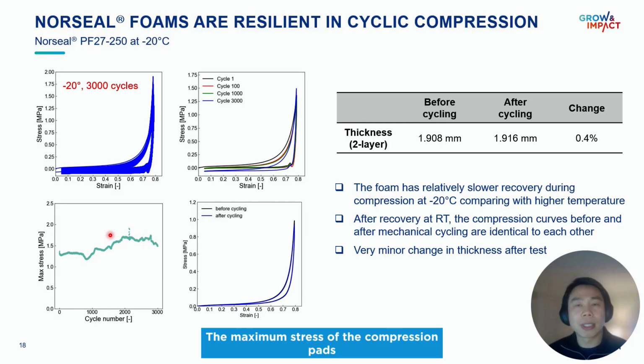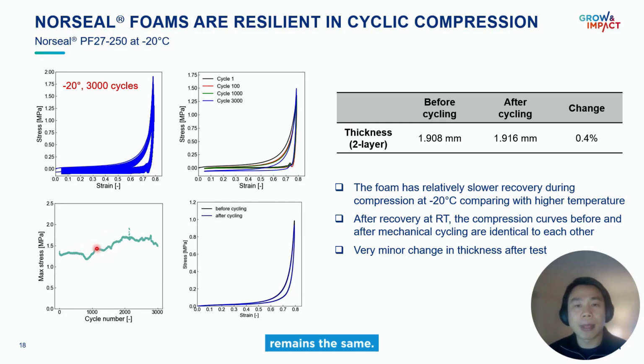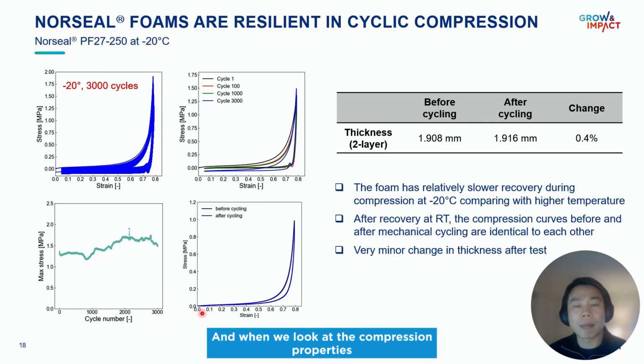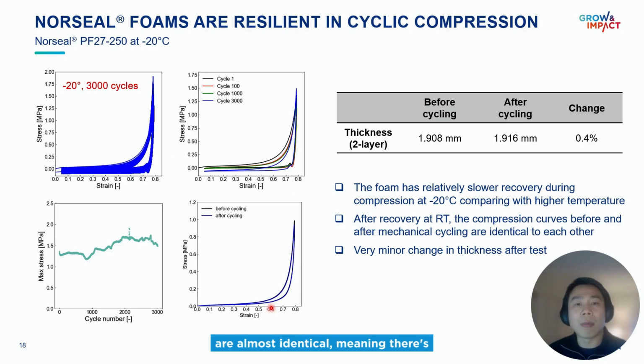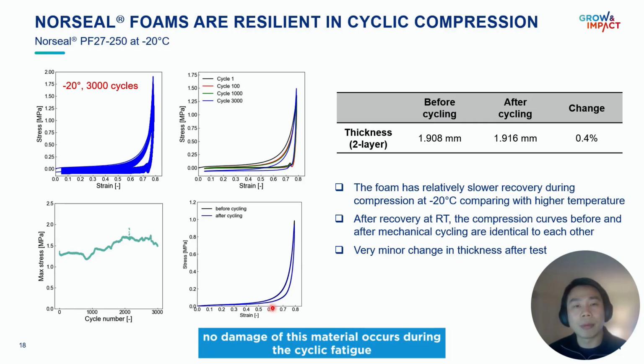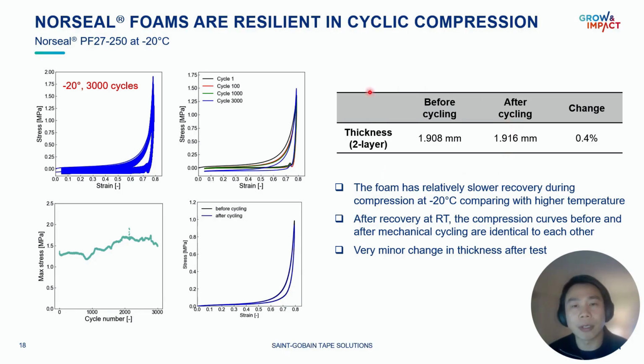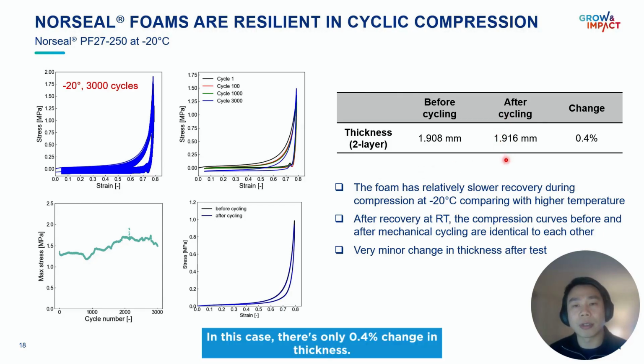The maximum stress of the compression pads remains the same. And when we look at the compression properties of these compression pads before and after 3000 cycle at minus 20 degrees C, the compression properties are almost identical, meaning there's no damage of this material occurs during the cyclic fatigue testing. Again, this can be seen from the comparison of the thickness change before and after cycling. In this case, there's only 0.4% change in thickness.